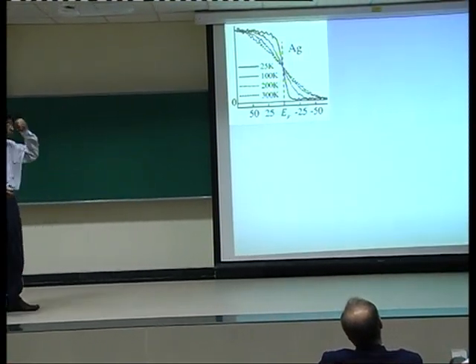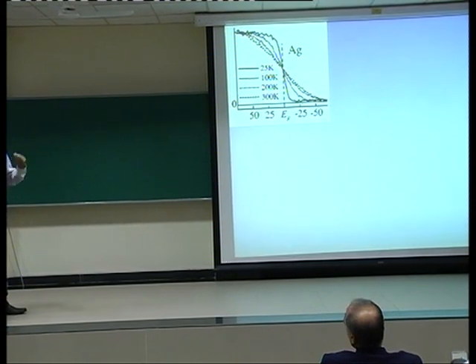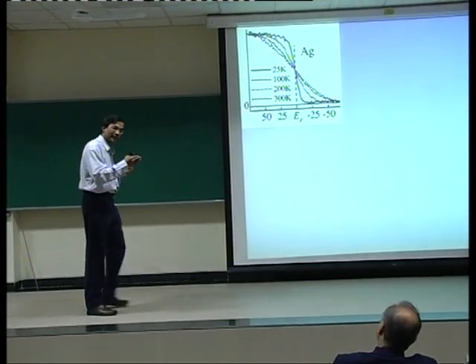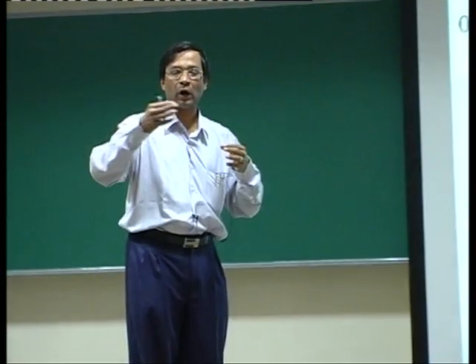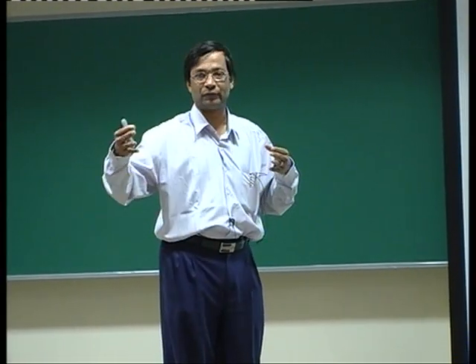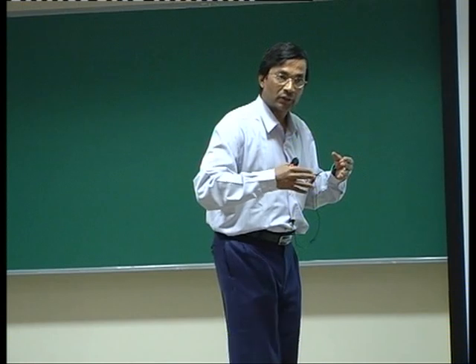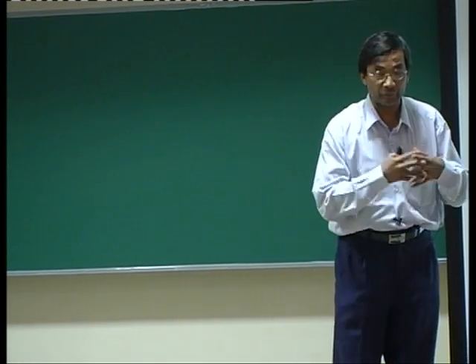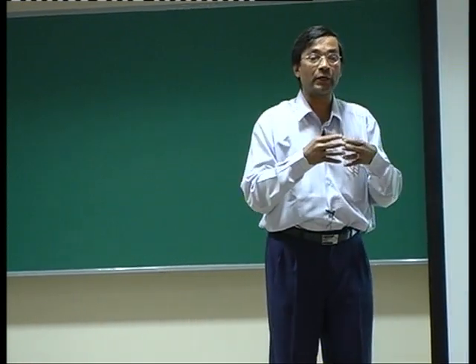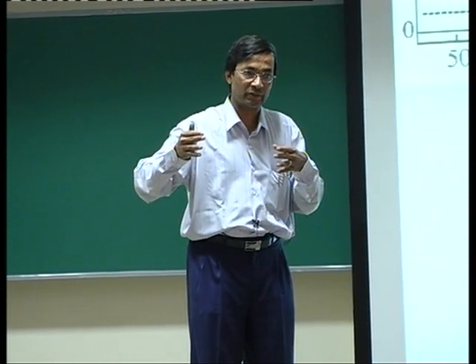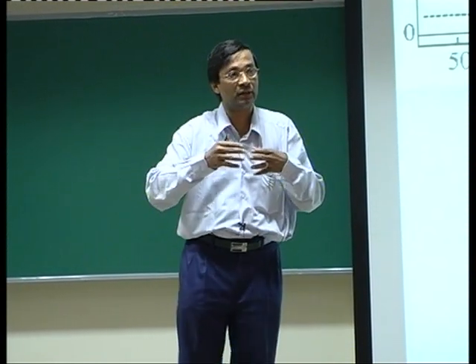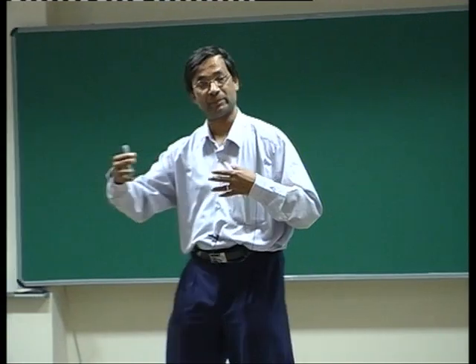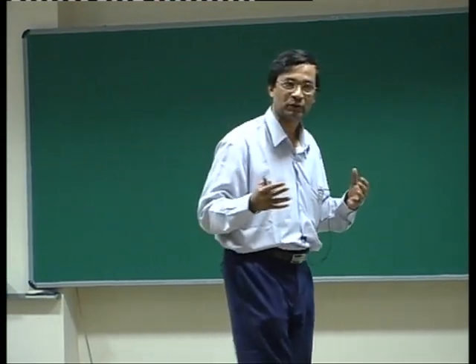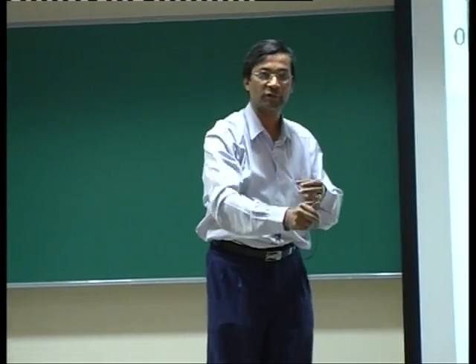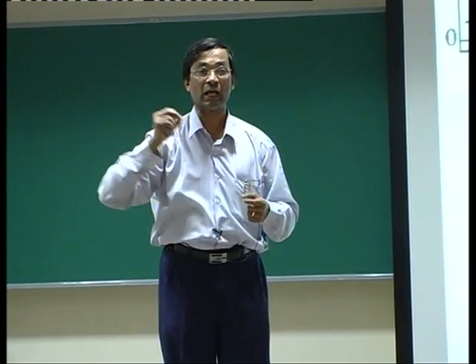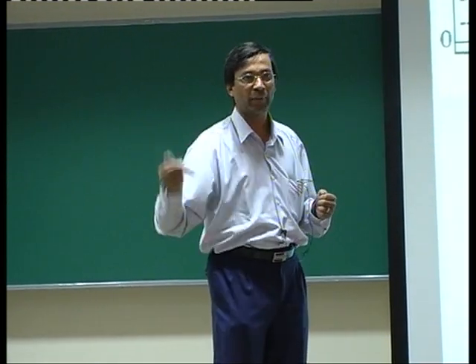Before I do that, I would like to show you the point that it actually looks like a metal, not only by the fact that we don't see a gap opening up, but we can also probe how the spectral weight is above the Fermi energy in photoemission with great accuracy and tremendous amount of resolution, because what we can do is systematically change the temperature of the sample. As we change the sample temperature, I'll be populating across the Fermi energy if it is a metallic state, or insulator depending on the gap size, and I'll be able to block out electrons from above the Fermi energy in the process, and I'll be able to map out what exactly it looks like above the Fermi energy.